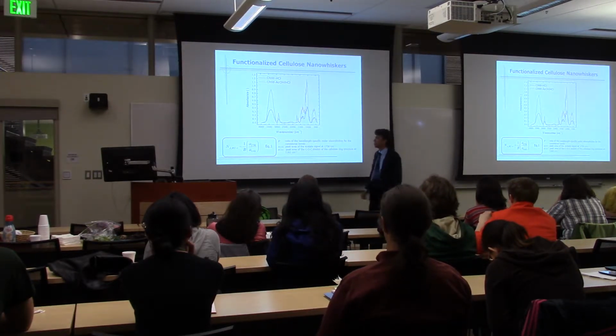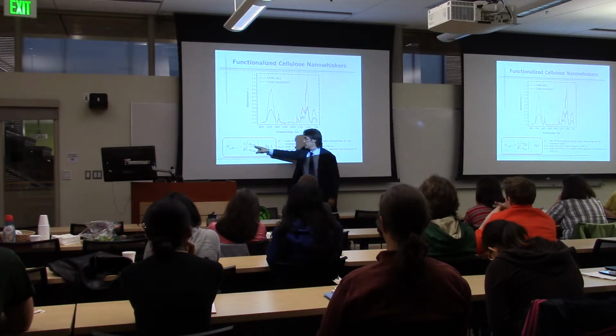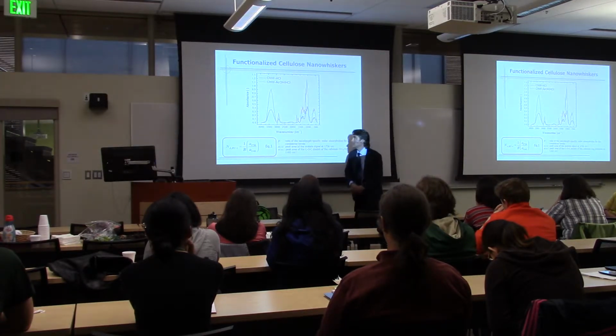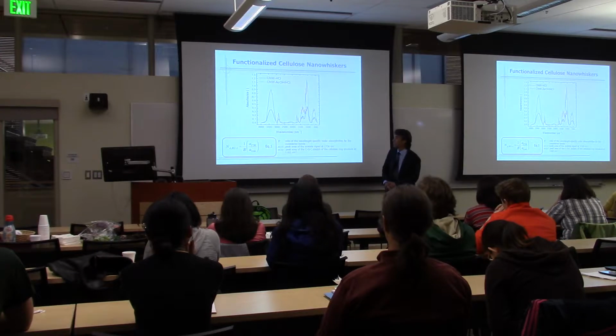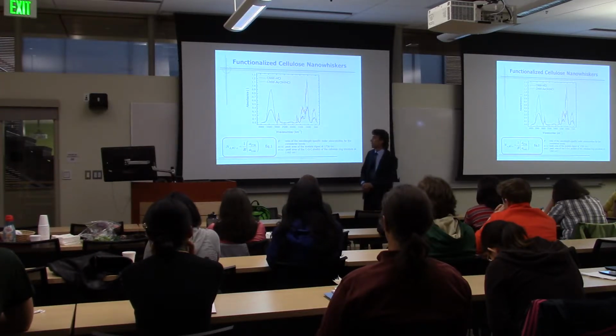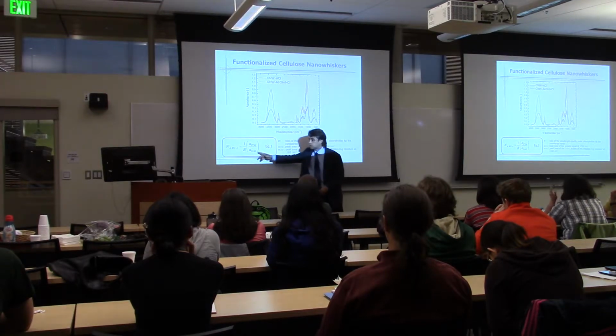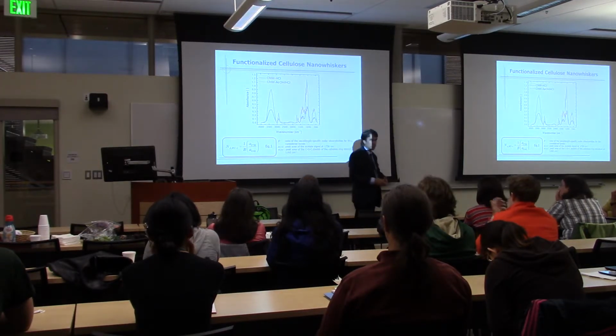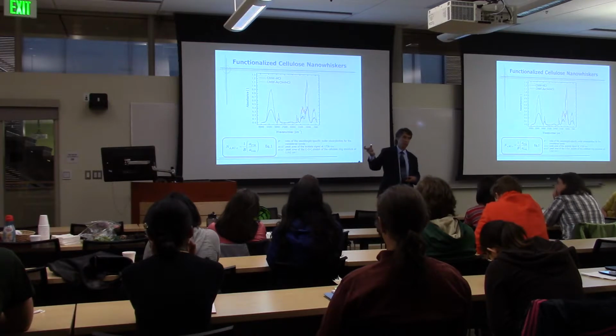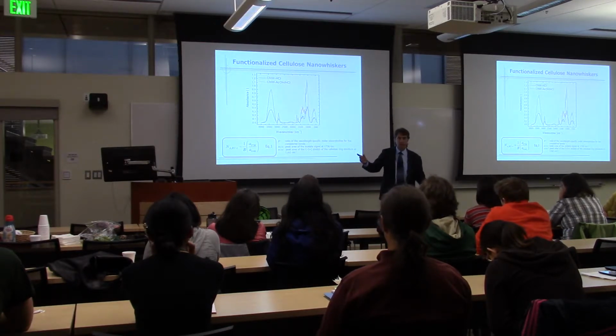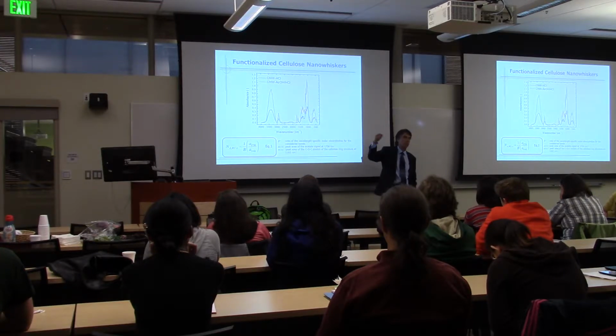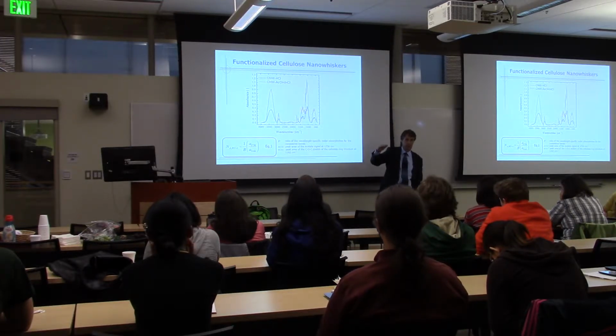So the absorption at 1736 wave numbers is the absorption due to the acetate group. And in addition, there's an absorption band at 1162, which has to do with the cellulose structure itself. So if you take the ratio of those two, because FTIR is quantitative, what you've done is you've counted how many acetate groups you have per ring in your cellulose structure, okay? So you're counting acetate groups to total amount of cellulose.